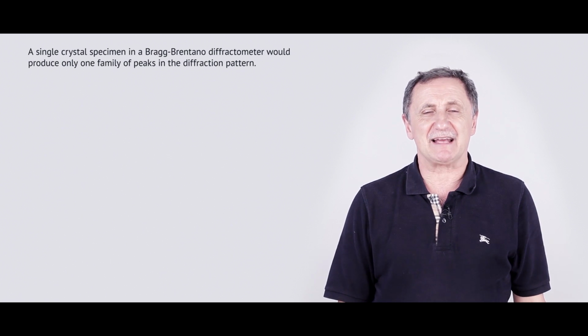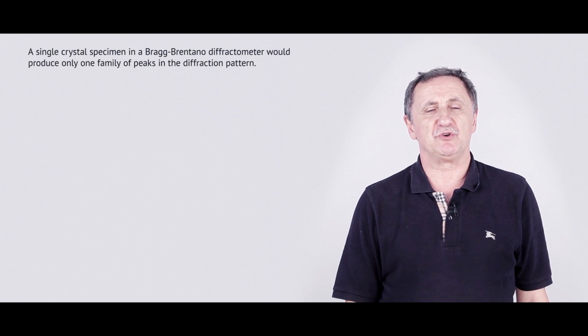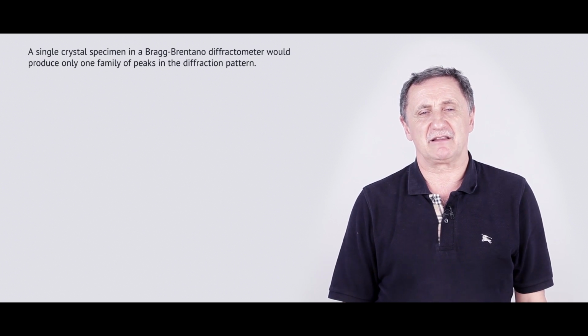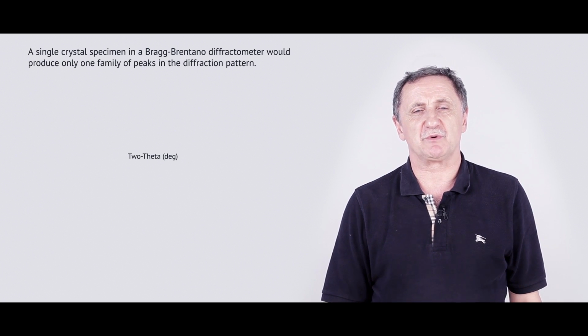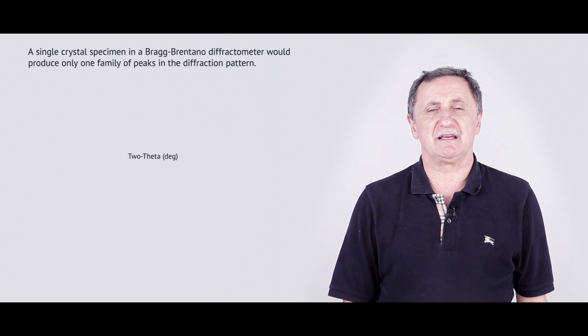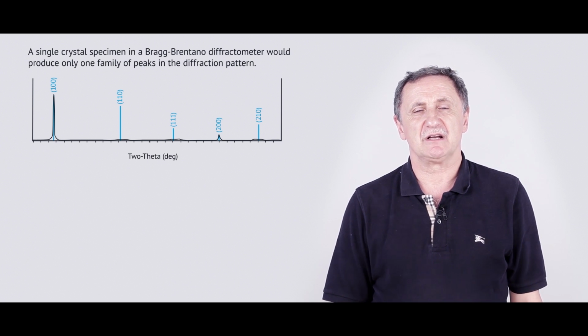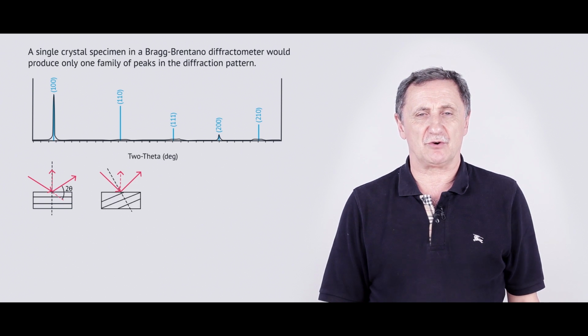hours. On the other hand, again just for the general information, if you use extremely strong synchrotron radiation as the X-ray source and linear type detectors, you can obtain the XRD pattern in some range of diffraction angles in a time span of microseconds. You have to remember this also.